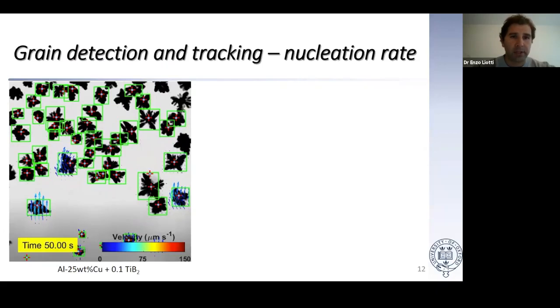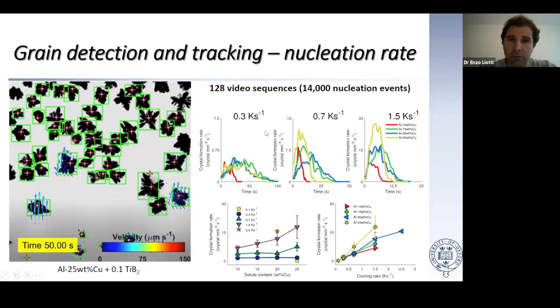Maybe the counting, yes, but tracking 4,000 grains and their growth is unrealistic. One use of this data is summarized in this table, which accounts for 14,000 nucleation events. This is the kind of number, right? Bear in mind that in solidification, as in the presentation before, experiments are quite difficult, so collecting data is not so straightforward. Being able to record hundreds or thousands of videos and then manage to extract 14,000 points is a great thing, also because then you can start to look at correlations between various parameters and look at the phenomena from a statistical point of view.